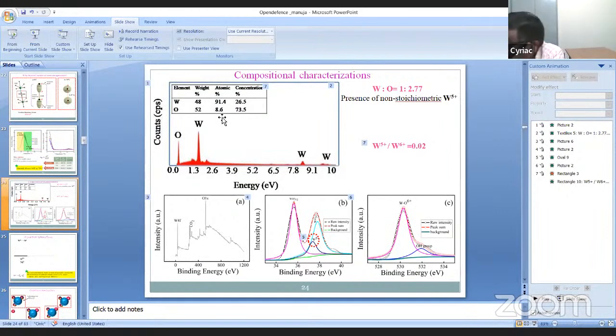Then how will you differentiate the presence of W6+ and W5+ from the EDAX? They have already given that there are tungsten and oxygen atoms present in the compound, and the oxygen and tungsten atom concentration shows that there is non-stoichiometry in the compound. So we took XPS to identify the non-stoichiometry. We use XPS and the EDAX result. Then XPS is taken to identify the presence of W5+ and W6+ separately.